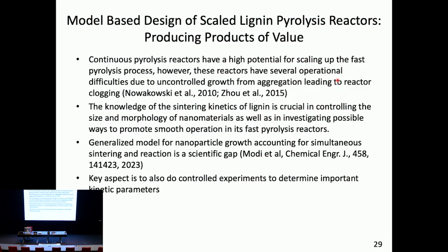Now I want to say, okay, it's working. Can I scale it up? Can I have a continuous pyrolysis reactor? And so forth. This is where you really want to crank up those models I talked about. But there's a practical issue with sintering. When I want to increase the yield or the throughput, because of the higher concentrations, I have collisional growth, and they form agglomerates, and then they sinter, and they actually plug up these reactors, right? So we really need to understand and suppress that process, so that I can continuously run my pyrolysis reactor.